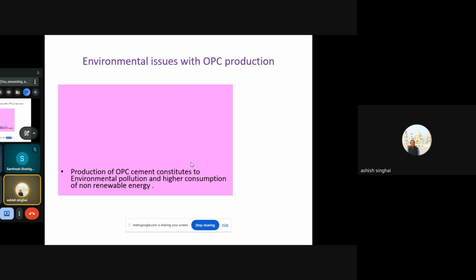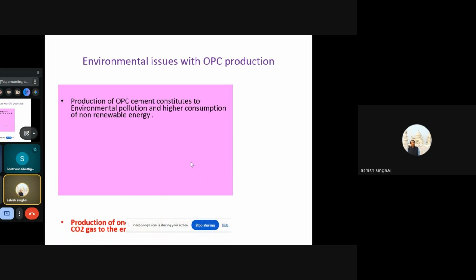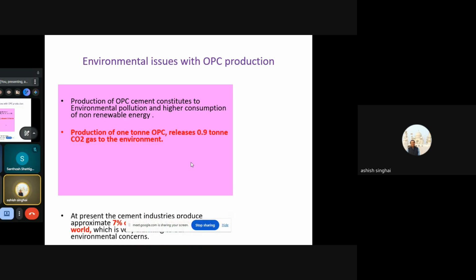As we know, every single ton of cement produces almost 0.8 to 0.9 tons of carbon dioxide gas that goes into the environment. So OPC has to be totally ignored, or possibly rejected at the sites, and only blended cements, LC3, or possibly geopolymer concrete have to be promoted. So that gives a broader picture.